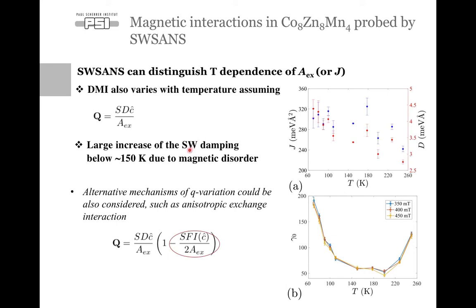Also, as I already said, we have a very large increase of the spin wave damping. So here the spin waves are damped just because of the fluctuations near the paramagnetic transition. But very surprisingly, the spin wave damping also increases dramatically as we pass around 150K. And again, we relate it to the frustration of manganese moments at 12D site and the short-range correlations that also exist in this 884 material.